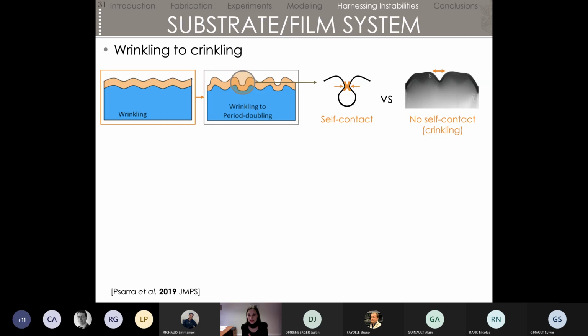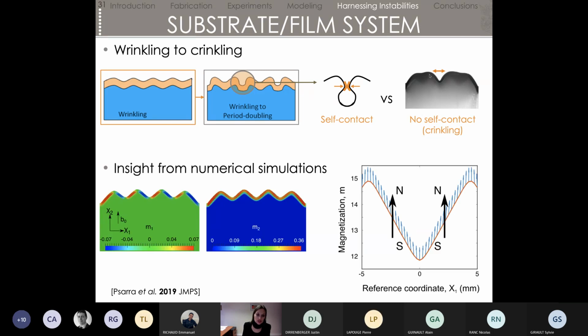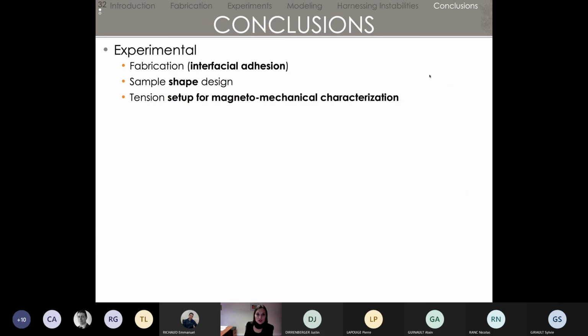So there was some kind of discrepancy between the shapes that we could see mechanically and the ones that we were obtaining under magnetic field. And so here, the simulations helped us understand what was going on. In fact, even though those two sides should have touched themselves, because they are magnetized and the magnetization remains along the direction of the applied magnetic field, they were actually pushing themselves away. And so that's why we never saw self-contact as could have been observed before in purely mechanical tests. So that's the main result of that simulation.